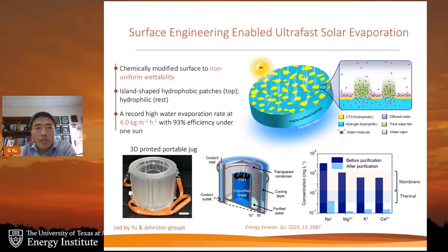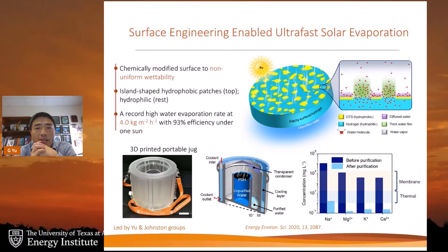Another finding involves controlling surface wettability states — tuning between hydrophilic and hydrophobic states. With increased thickness of the water layer in the hydrophilic regime, there is very rapid water molecule escape, and the long contact lines between hydrophilic and hydrophobic regimes enable very high water evaporation rates. We also demonstrated a 3D-printed portable solar water purification system suitable for point-of-use water purification applications.